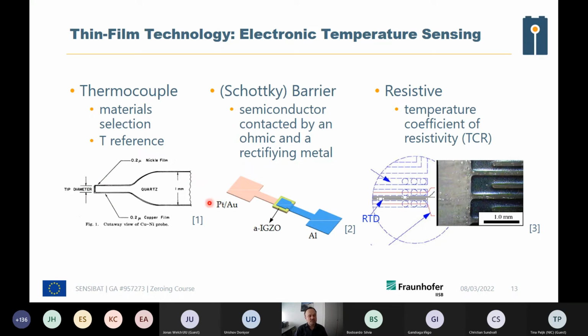So it has to be clearly stated that there are a lot of requirements to be fulfilled to get a proper measure of this voltage that is available here on the inside. For example, the two connection points to the outside must be on the same temperature level. There doesn't have to be any deviation between the temperatures at these two points. Otherwise, the work function differences here would add up and would give a distortion on the signal that you find here. Also, it must be a well-defined contacting scheme to the outside.